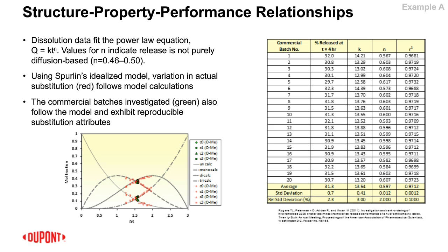That graph on the left-hand side, just in a nutshell, what we're talking about here is, these polymer chemists I was referring to, they have the ability in the R&D lab or in the pilot facility to design in more substitution heterogeneity along that cellulose backbone, right? And those are those red points that you see there in that graph. And then our 20 samples from commercial batches of Methocell K4M, those are the green dots that are essentially right on top of each other in that lower left-hand graph. So it gives you an idea of really what we're talking about in terms of grand scheme of things, variability from batch to batch of these 20 commercial K4M materials.